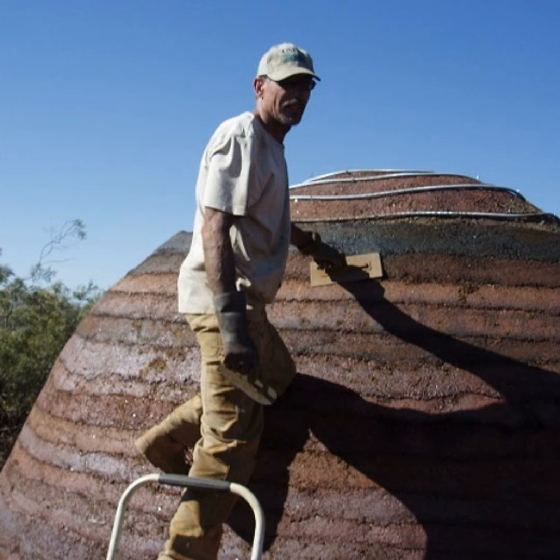What I was able to discover is that you can use CO2 instead of regular oxygen, O2, and have the iron react with CO2 and bond with that and make an iron carbonate. So it's not just iron and oxygen, it's iron and CO2, carbonate, actually, CO3, iron CO3. So it's a little bit of a reversal of the cement process, right? Because the cement is driving off CO2 from a carbonate, calcium carbonate. I'm taking the CO2 back out of the atmosphere, combining it with raw, pure elemental iron and making an iron carbonate. But how did you know this would be a good binding agent?